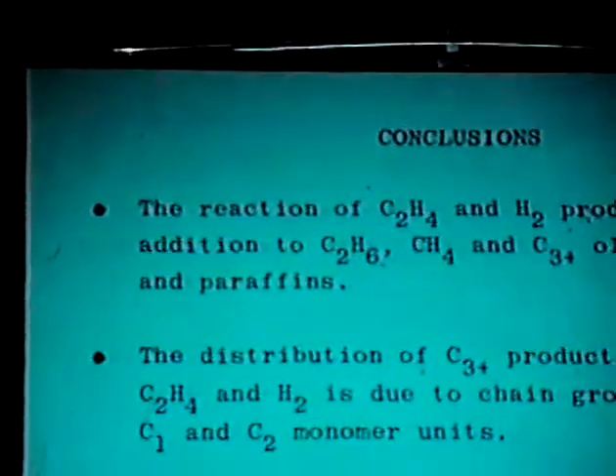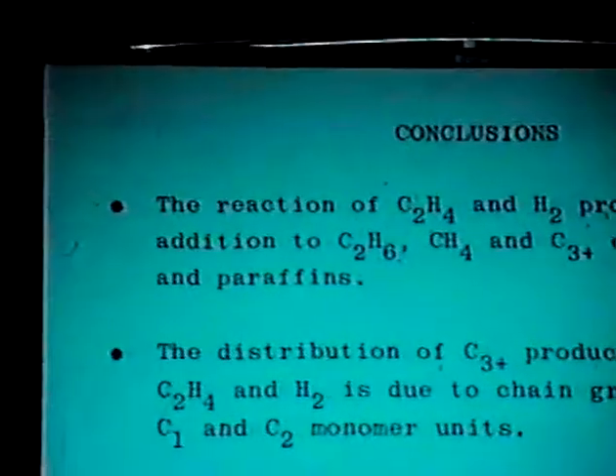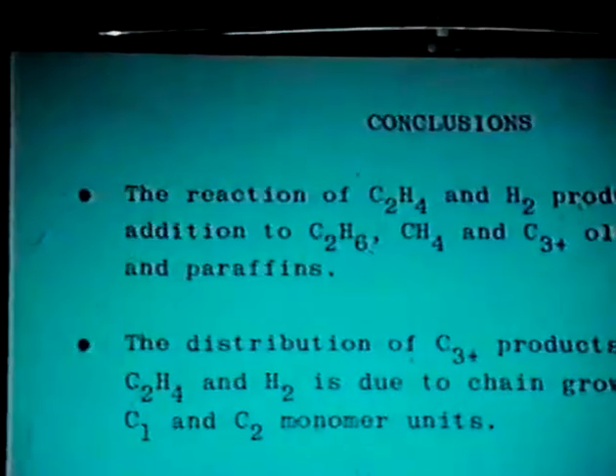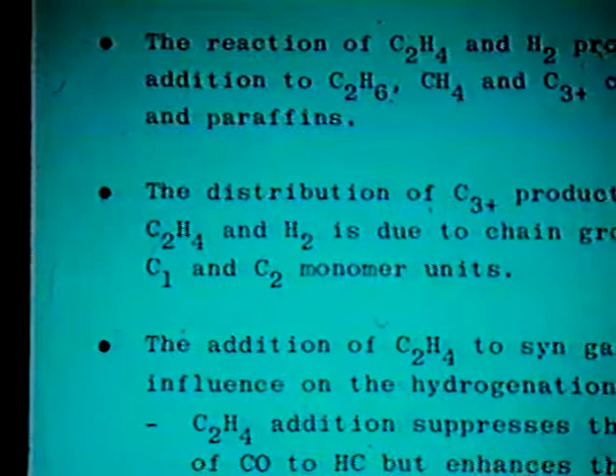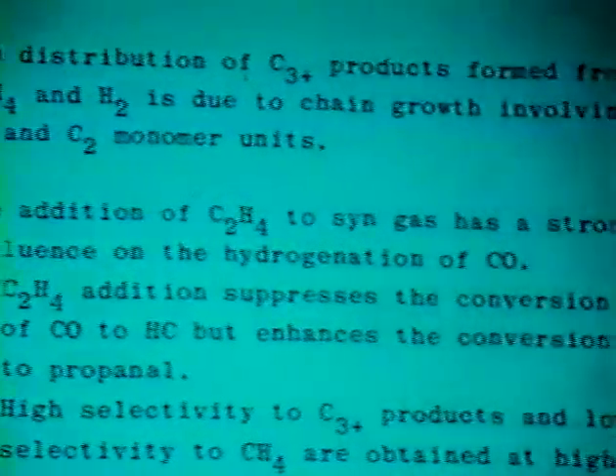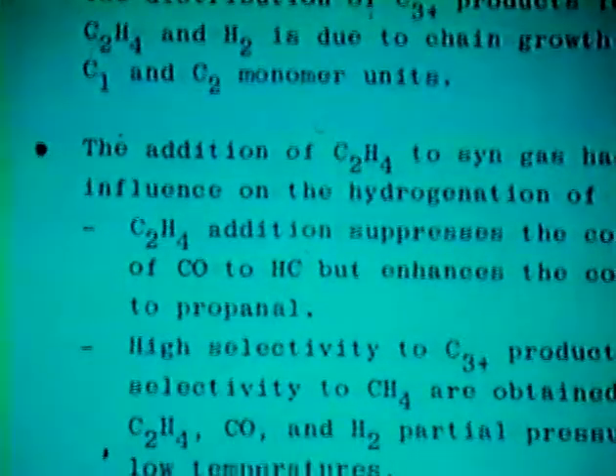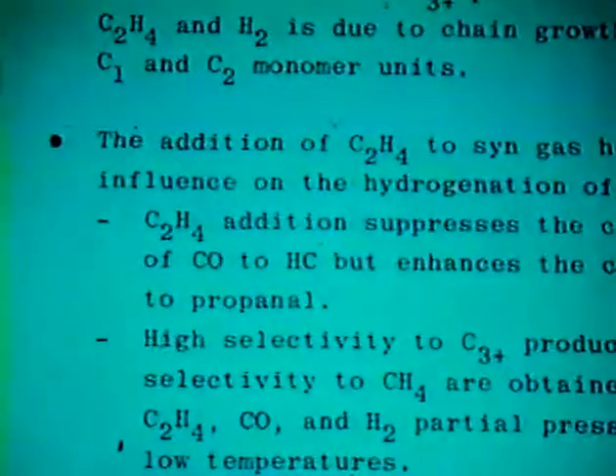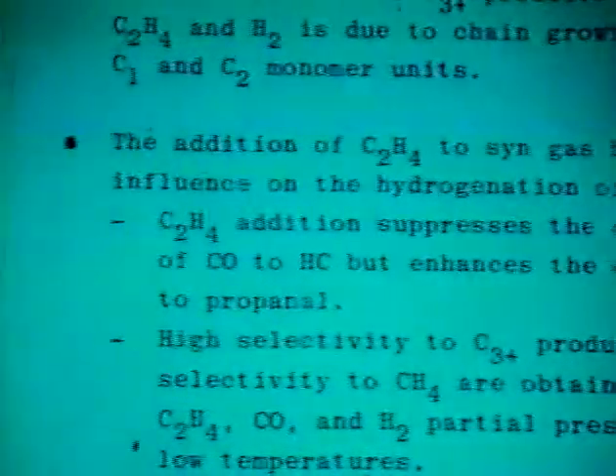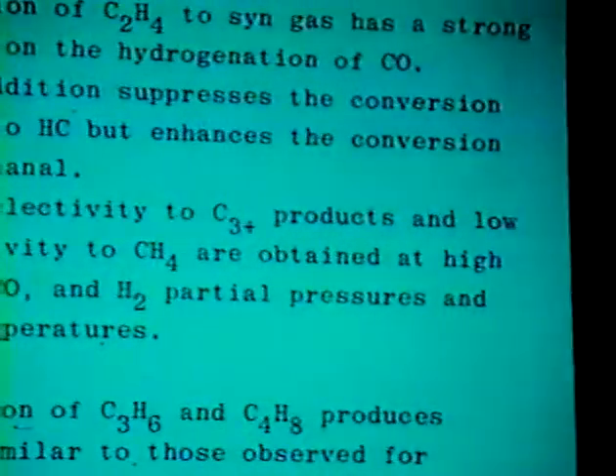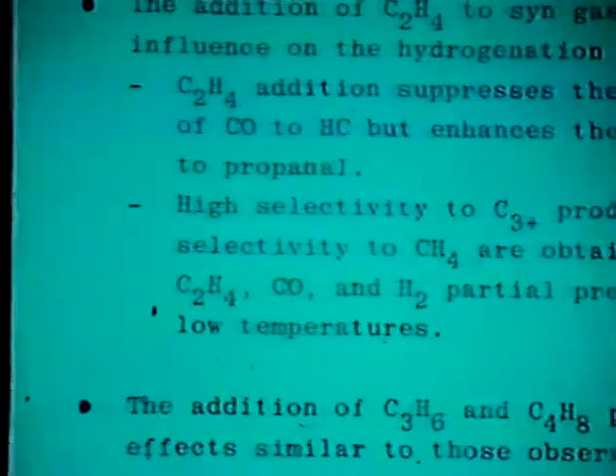The conclusions of this part of the study show that olefins are not passive products, but they do add back to the chemistry in a very complex fashion. As a source of intermediates for chain growth, they turn out to be more active than even CO. They react with CO to produce aldehydes and alcohols, and they offer the possibility of possibly tailoring the product distribution that we observe from Fischer-Tropsch synthesis, namely the concept that we might be able to feedback the olefins and thereby change the product distribution. Since I see the chairman has risen and my time is up, I will conclude on this note and thank you for your attention.